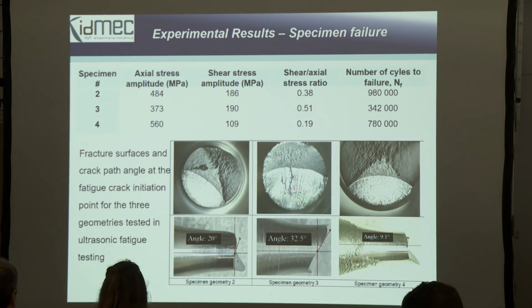So three different stages for three different shear to axial stress ratios. Of course, we have different crack proportions, but also we can measure the inclination of the initial crack, because it depends on the shear to axial stress ratio, as already observed in servo-hydraulic tension torsion fatigue testing machines. So we also have quite a lot of experiments in servo-hydraulic ones, and this is coincident. So we think that this is correct, either in ultrasonic fatigue or in the servo-hydraulic ones.